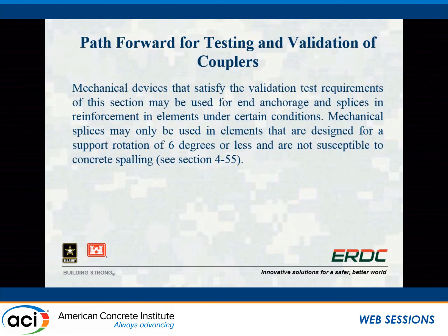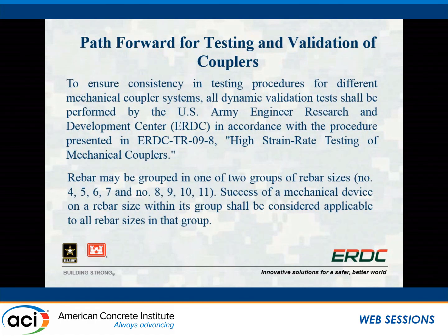So how we're going to incorporate this into UFC is, so now we can use mechanical devices, mechanical couplers for connections to replace lap splices in congested zones in reinforced concrete systems, with some provisions based on confinement that needs to be provided by the concrete, especially in areas that are prone to spalling and things of that nature. And so the guidance for actually doing this testing has to be done in our laboratory according to the guidance provided in this TR09-8. And based on some additional testing that Steve and his group actually executed, they've divided that into 2 different size ranges where tests have to be performed depending on when and where the couplers are actually going to be used. Most oftentimes that's going to be on larger bars, but in some cases, may also be applied for smaller bars, especially for retrofit applications and things like that.